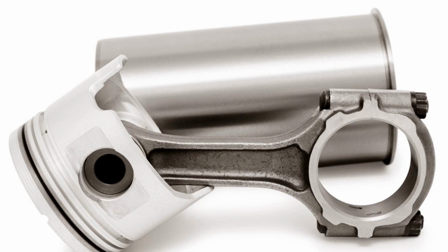Already in the early 70s, engineers switched to the active use of dry cast iron liners inside the aluminum block. Technically, it was difficult to press the heated cast iron liner into the softer aluminum. Plus, both metals have different coefficients of thermal expansion. This resulted in gaps between the liners and the block walls when the engine reached its operating temperature. Aluminum did not surpass cast iron in stiffness, but the overall weight of the block was reduced significantly.